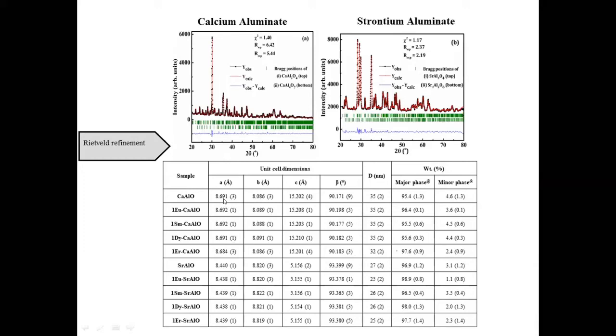the monoclinic phase. a is not equal to b is not equal to c. Alpha and gamma, they are 90 degrees. And that is not equal to beta, that is slightly deviating from the angle of 90 degrees. So these are the structural parameters, the unit cell dimensions. And almost 95% of the phase is CaAl2O4. The other phase is very small, about 5%.